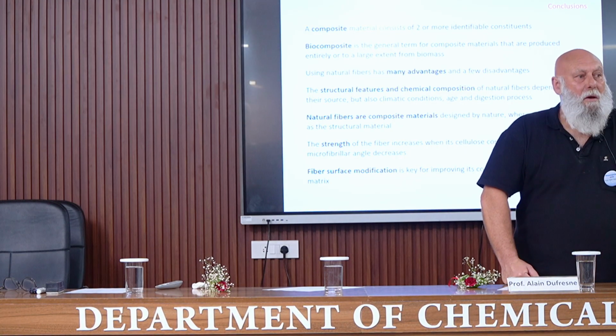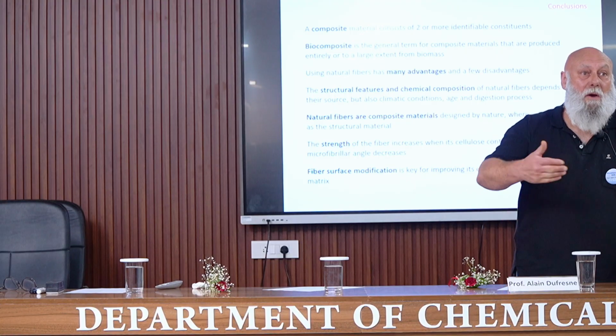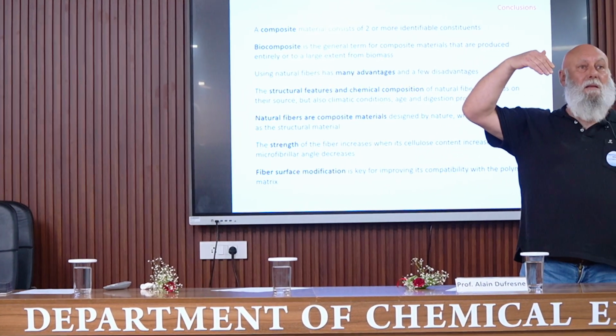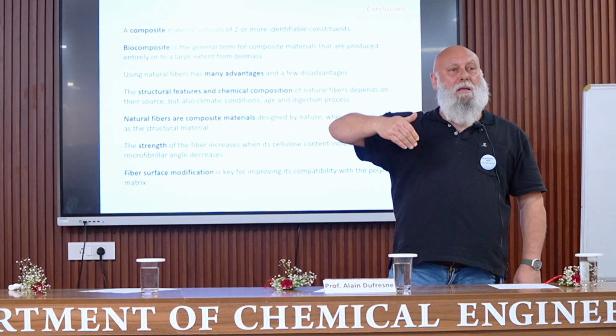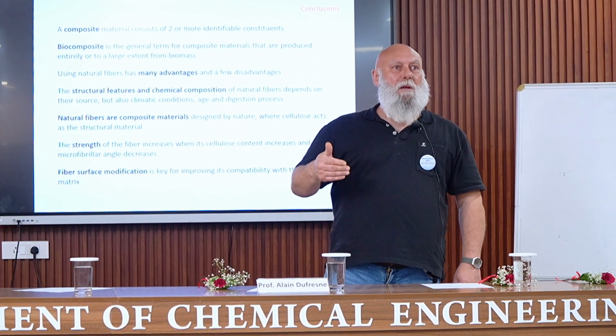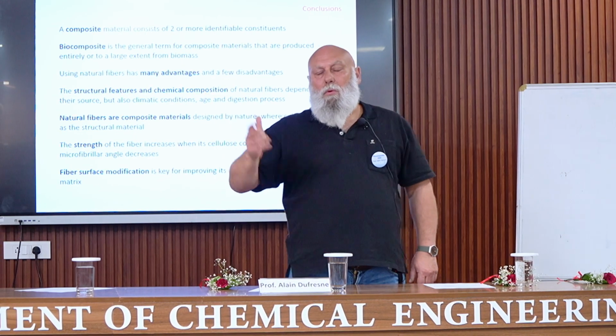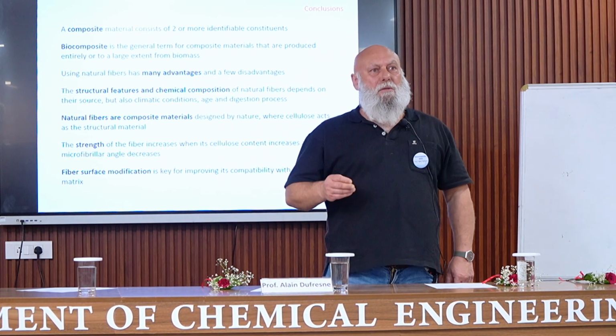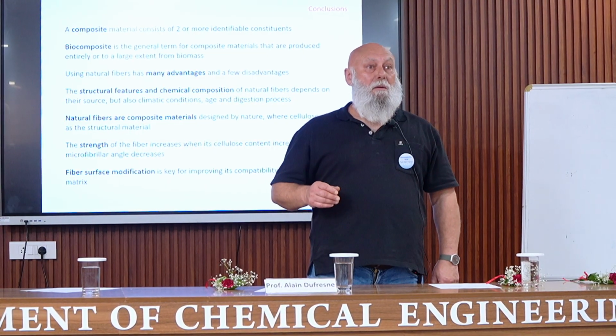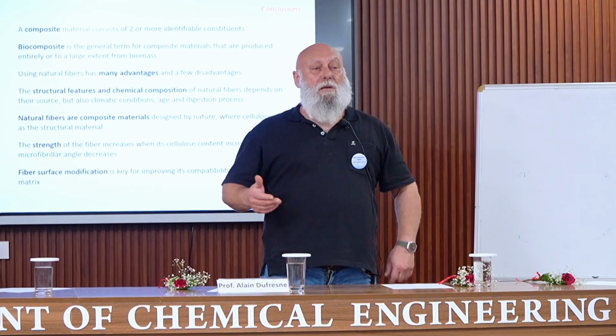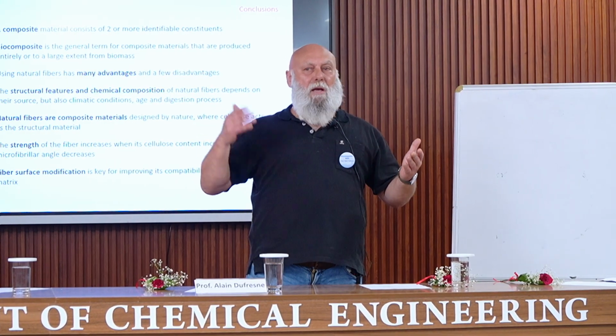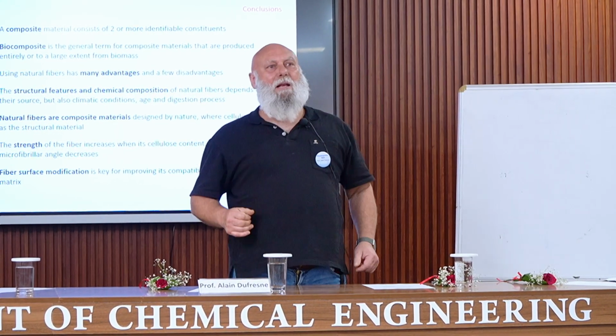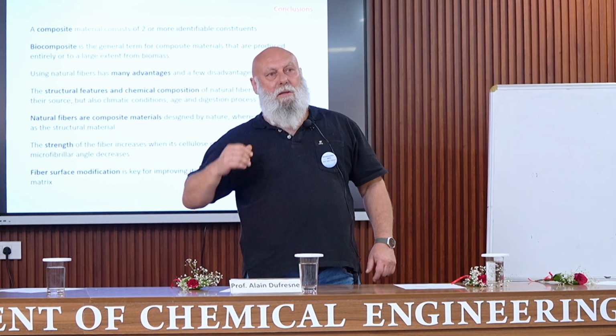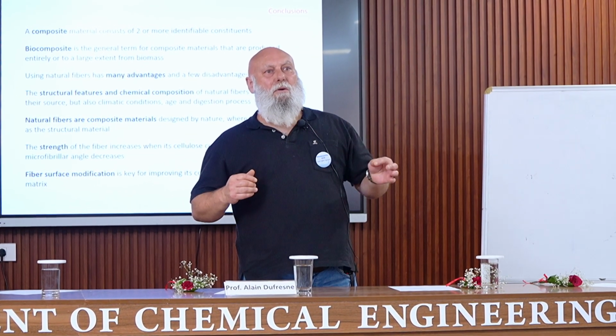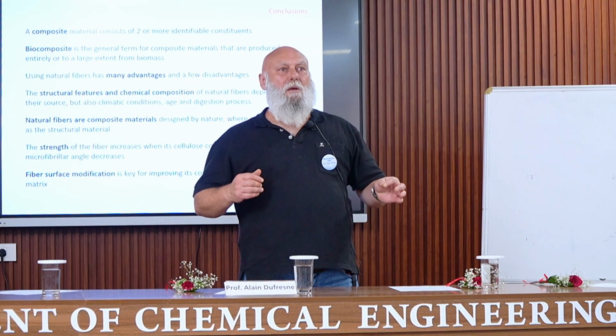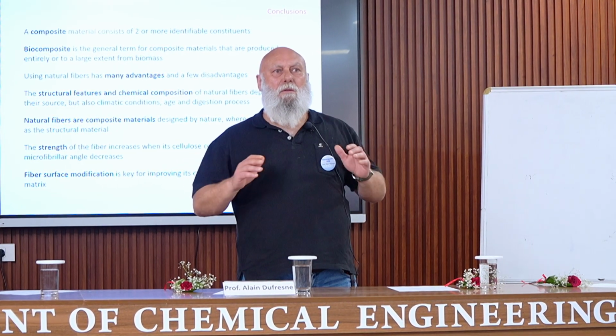Yes, it can be an alkali treatment that removes at least part of this material. And then to remove the residual lignin, we can use a bleaching treatment. This treatment, I don't know very well, but they are classically used in the pulp and paper industry. Otherwise, it's possible, I didn't highlight this in the table, but some sources of cellulose are very rich in cellulose, meaning that there is almost no lignin, no hemicellulose.